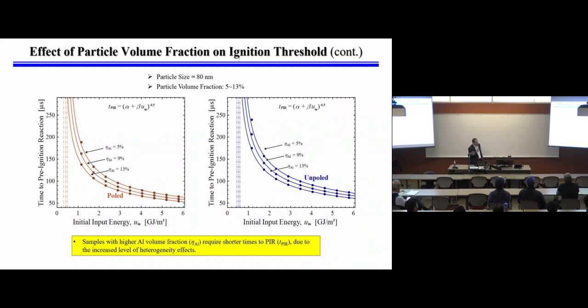The last slide I wanted to show now is if you keep increasing the aluminum particles, you keep increasing heterogeneity, you can actually enhance the ability, meaning that if you only have 5% particles, then things happen more slowly. But if you increase the particles to about 13%, then you can make the threshold happen much earlier, things much faster. So having more aluminum, having more energy for chemistry anyway, also helps with getting the chemistry going more quickly for both poled and unpoled materials.